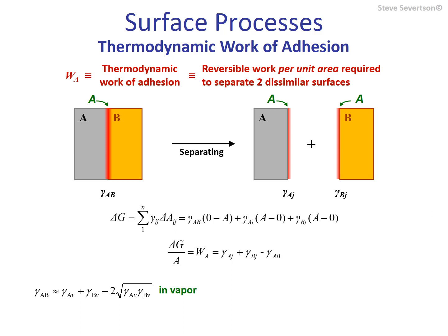Keep in mind that this process could be carried out in a liquid rather than in air or vapor. Under these circumstances, the equation for estimating interfacial energy must be used to approximate all interfacial energy terms. Furthermore, it is possible to split the surface energies into polar and dispersive components, which is thought to provide more accurate estimates of the thermodynamic work of adhesion.